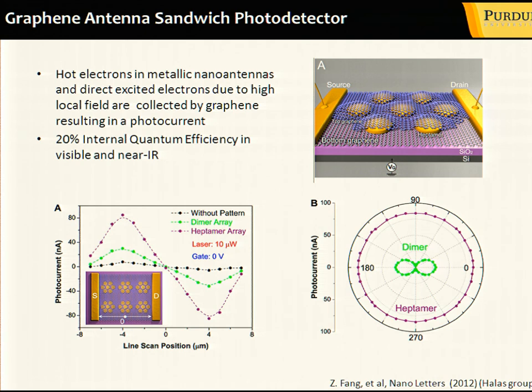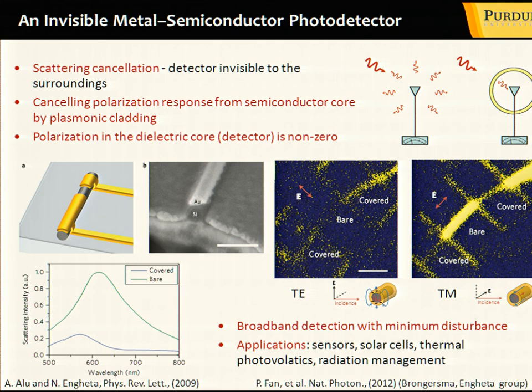Another important element of future nanophotonic circuitry is, of course, the photodetector. Here you could see recent work coming from the Halas group. They place plasmonic nanoantennas made of gold disks between two graphene sheets. In this case, you could generate a photocurrent using two mechanisms. One is by first exciting plasmons in nanoantennas, and then plasmons could decay into hot electrons, which could be transferred to graphene, or by just using the locally enhanced field of these nanoantennas, which directly excites charge carriers in graphene. The surprising thing is that this photodetector has extremely high internal quantum efficiency, at the level of 20%. That's a very impressive result.